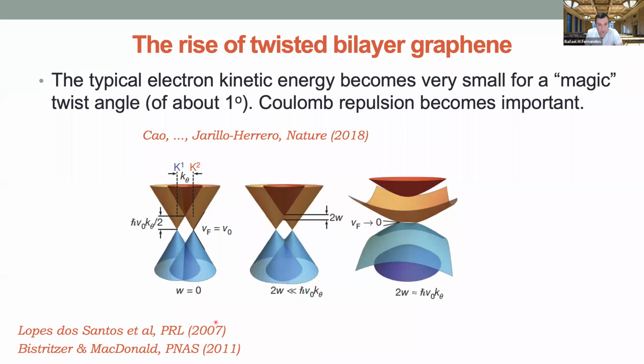And what was proposed years ago in these papers, and this very famous paper by Bistritzer and MacDonald, was that if you choose this angle just right, you get a nearly flat band. So the physics is simple: when I bring together these two graphene layers and rotate them, I'm hybridizing two Dirac cones, and the hybridization opens a gap. If this gap is comparable to the distance between the Dirac cones, I can essentially lead to a vanishing of the velocity, which would lead to a flat band.